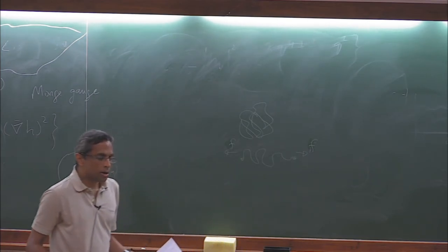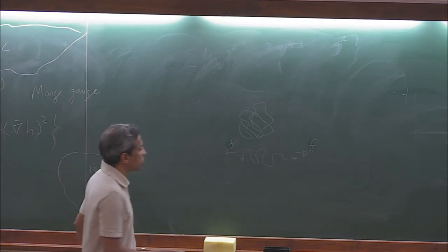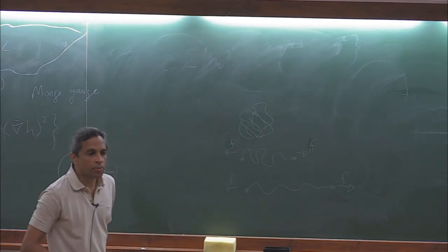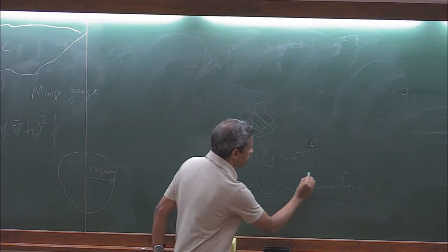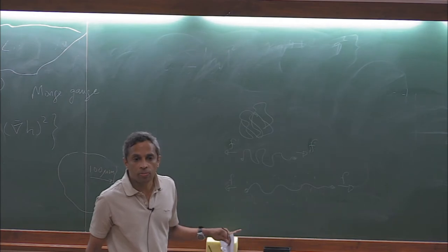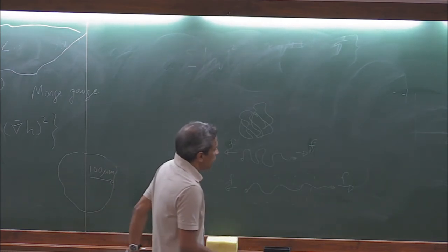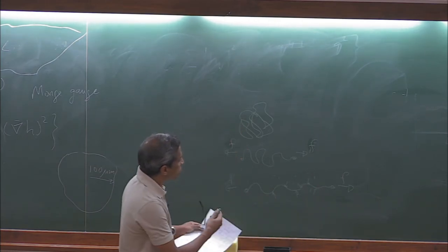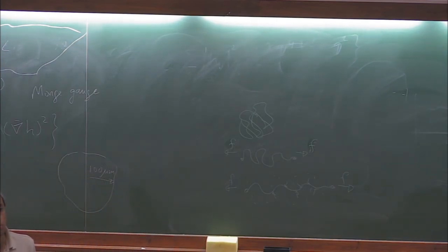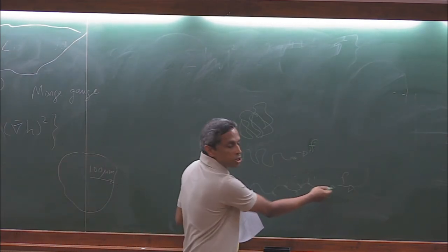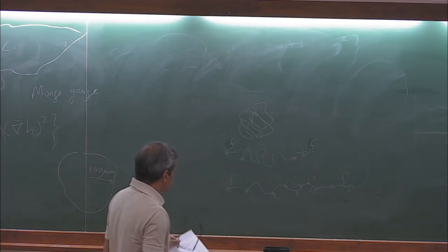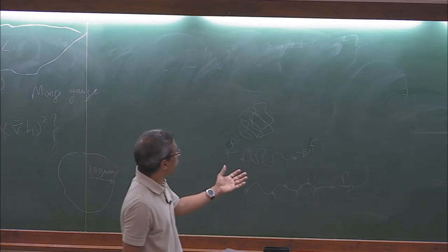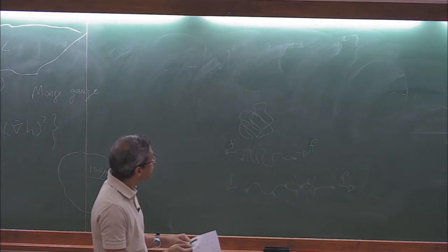A simple way to ask what is the microscopic reason for this, and you can tell me if this is a reasonable way of saying it: if I apply a force and stretch the polymer, what is happening to the polymer? This polymer is in a liquid medium, okay? That means the water molecules are constantly bombarding against this polymer. That is where the fluctuations come from. Now, in this kind of geometry, you will see that no matter in what directions the microscopic collisions occur, these collisions always try to maximize the conformations the polymer can explore. In other words, these collisions always try to pull these two ends together. But the way you calculate it is you just calculate the entropy. You calculate the number of conformations the polymer can take, and from that you can show that this polymer behaves like a linear spring for very small deformations.